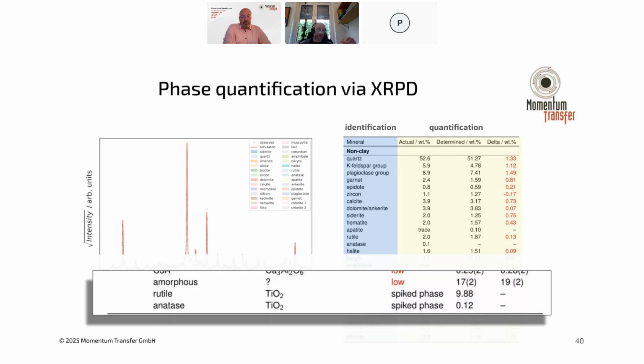In cases where you have a large amount of amorphous material present, then there are different methods to estimate the amorphous content as well. So we typically use a method called the internal calibration method, where we add a known weight percent of a reference material into the sample. So in this case, for instance, a bit of titanium dioxide. And from that, we can renormalize all of the values of the identified phases and then subtract that from 100% to get back the amount of amorphous phase.